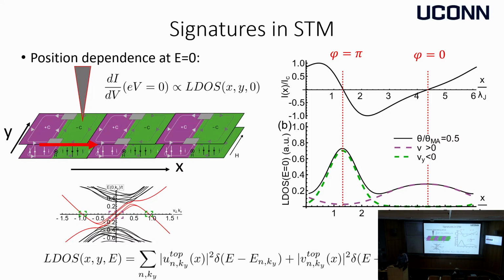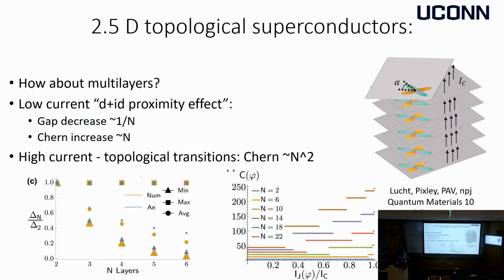Okay, let's see. With the time that I have, I'll just briefly mention some offshoots. We considered doing a twisted bilayer, but at this point experimentally it is a great challenge. Despite my showing you a monolayer that's superconducting as the bulk, taking two monolayers and transferring them on top of one another with a twist turns out to be much more challenging than for graphene. People are working on it, but it's hard. So what we did is, okay, let's simplify life a little bit. Let's take a stack of layers, just a flake with finite thickness, and then put one layer on top with a twist.